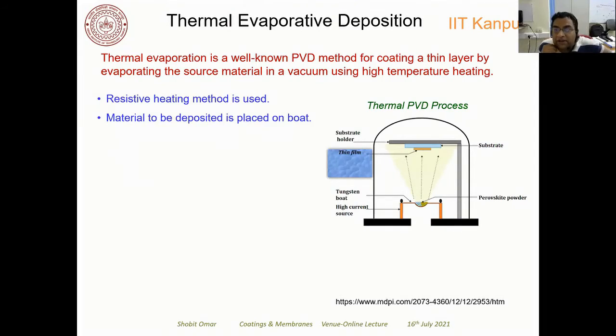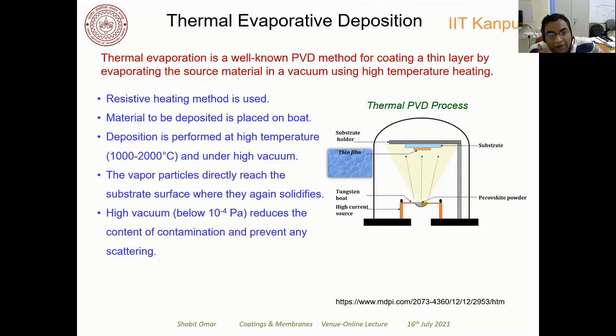So let's talk about the thermal evaporation deposition technique. As I said, there are two types of PVD. One is evaporation, the other is sputtering. Here I am talking about evaporation, and in evaporation you have the thermal evaporation deposition technique. As the name suggests, thermal evaporation deposition uses external heating to heat the target material, and that target material is converted into vapor phase, and that vapor is deposited on the substrate. A resistive heating method is used, and as you can see in this schematic, the material to be deposited is placed on some type of boat or crucible, and you do the external heating through the resistive heating method. Deposition is normally performed at high temperature, like 1000 to 2000 degrees centigrade, and under high vacuum.